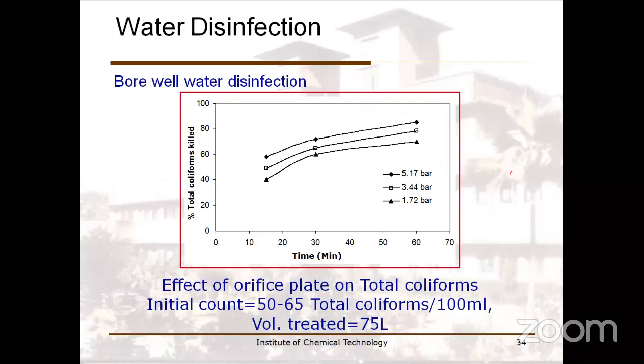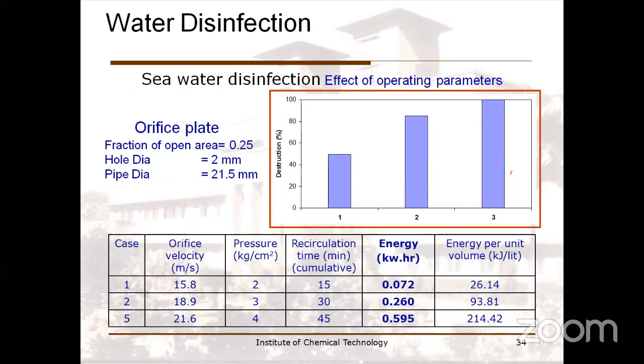Typically, bore well also has a lot of microorganisms. So if I want to treat it, can cavitation be used? So these are very initial studies which were done, and definitely there was disinfection in terms of the total coliform. Depending on the operating conditions, and treatment time of 60 minutes, you are able to achieve about 80% killing. So definitely it has disinfection capacity.